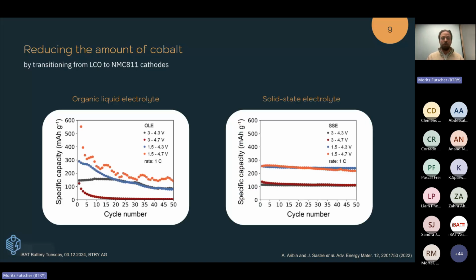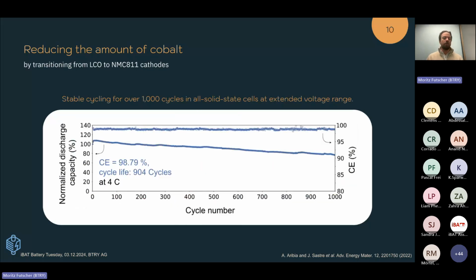This is very different if we have the same cathode in a solid-state electrolyte. If we use a solid-state electrolyte, first of all, we see that the cycling is much more stable, but also we can access a wider voltage range. Here, he showed that he can cycle from 1.5 up to 4.7 volts. And this is really only possible with the use of this LiPon solid-state electrolyte. He even showed that he could cycle this for 1,000 cycles, with a cycle life of 900 cycles when it reached below 80% of capacity.